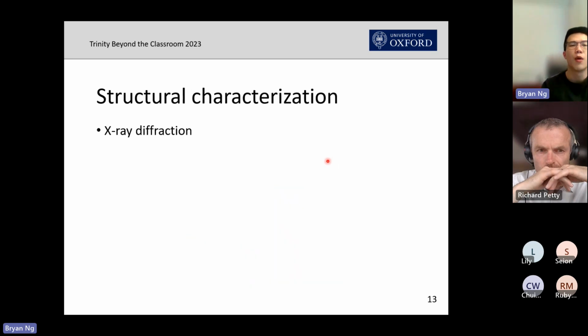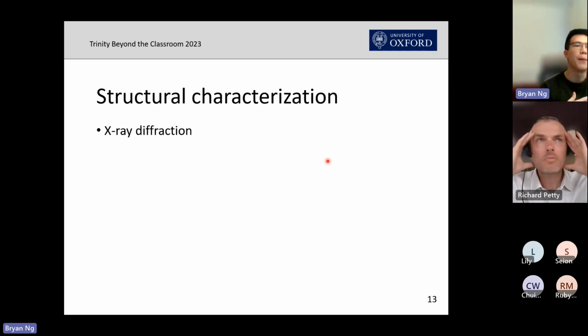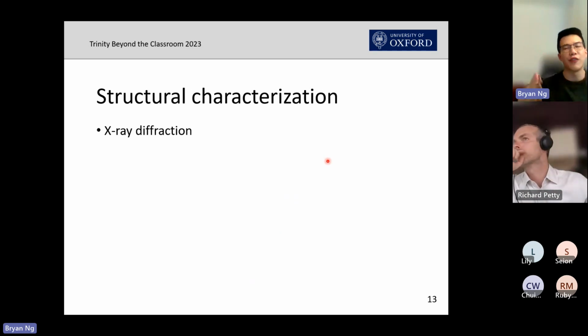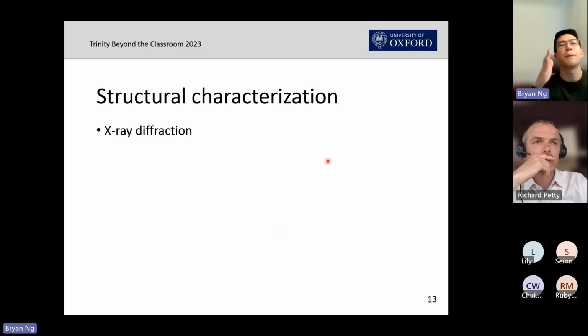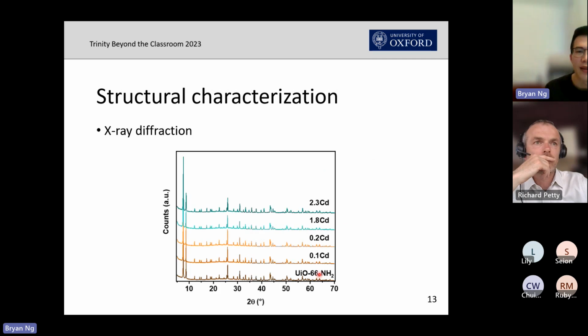So for example, one of the structural characterizations that is very frequently used is X-ray diffraction. It involves the different planes of atoms, and basically these different planes of atoms will give you a peak in this X-ray diffraction. And all of these samples give very similar peaks. So it shows me that the structure of these samples doesn't really change. And as a result, it's a good thing because we don't want the structure to collapse after adding the cadmium sulfide. Otherwise, there would be no point in me using this MOF as support.